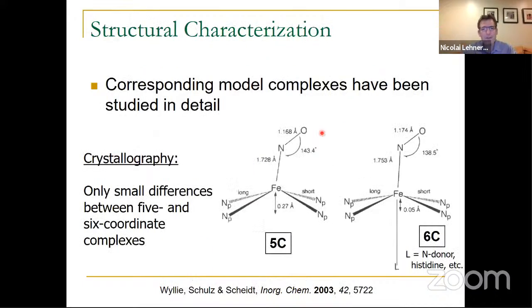Right, so here are examples from model complexes, and these are the structures of 5-coordinate iron 2 NO complexes, and here are the corresponding 6-coordinate complexes, and these are parameters that were taken from small molecule model complexes. And you can see, if you just look at the iron NO unit, so this part here, there's not a lot of a difference between them, right? These properties like iron N distance, 1.728 angstroms, 1.753 angstroms, these metric parameters are all very similar to each other. But one thing you notice is that in the 6-coordinate complexes here, the bond between the iron and the axial ligand is very, very long, right? And that, of course, in a way, is a reflection of this trans interaction here. That the ligand here in trans position to NO cannot bind very strongly.